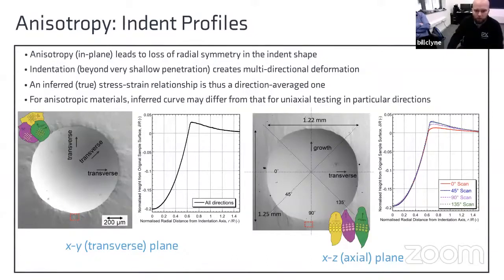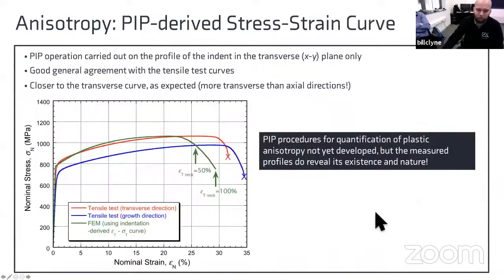So what can we do with this information? Well, if we take the radially symmetric indent, the prediction from PIP testing is shown on the plot here, and we can see that fairly good agreement is achieved. We would expect that, on the basis that indentation is a multi-axial procedure, so deformation will occur in all directions effectively, unlike in a uniaxial test where we're only testing in a single direction. And we see that the agreement comes out closer to the transverse direction, which is what may be expected given that there are more transverse than axial directions when indenting in this plane.